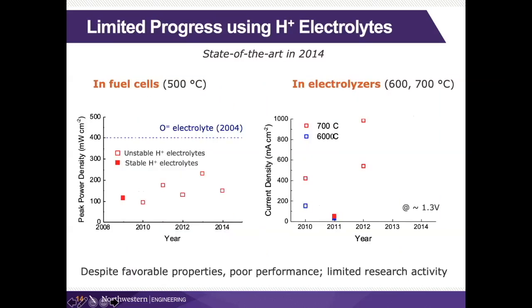So let me just tell you some of the progress now using these proton conducting oxide electrolytes. In about 2014, when we started looking at this and saying we should get involved in this because these electrolytes are really very good, I've just described to you all their features and why they ought to work. The state of the art in fuel cells, in terms of peak power density at 500 C, was really quite low, despite the fact that the proton conductors have higher ionic conductivity than the oxygen ion conductors.